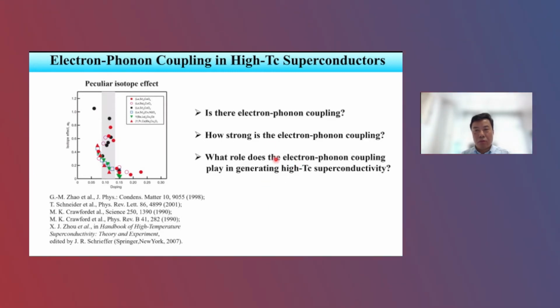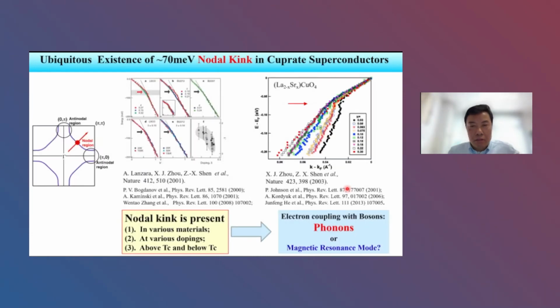we still want to know, is there electron-phonon coupling in cuprate superconductors? How strong is the electron-phonon coupling? And then what role does the electron-phonon coupling play in high Tc superconductivity? So I think ARPES is a very powerful tool to directly probe the electron-phonon coupling or electron-mode coupling in quantum materials. Because usually, if there is an electron-phonon coupling or electron-mode coupling, it shows up as a kink, just a slope change, a so-called kink in the dispersion.